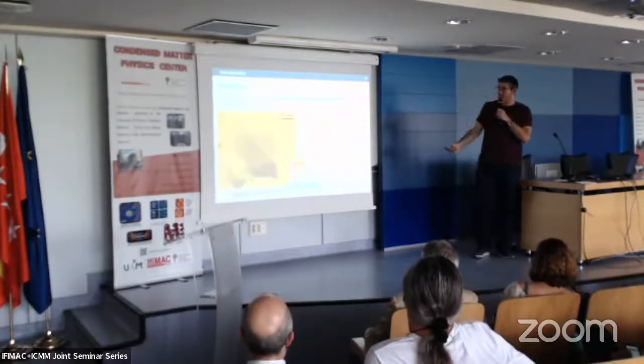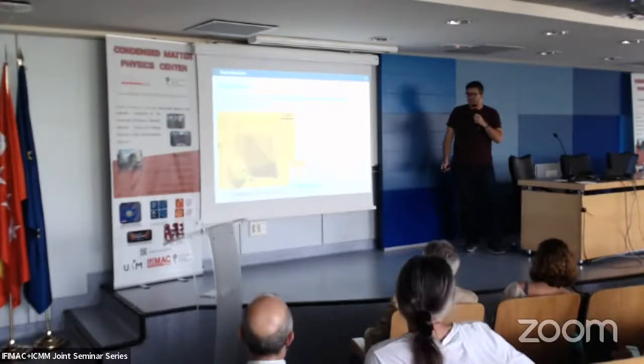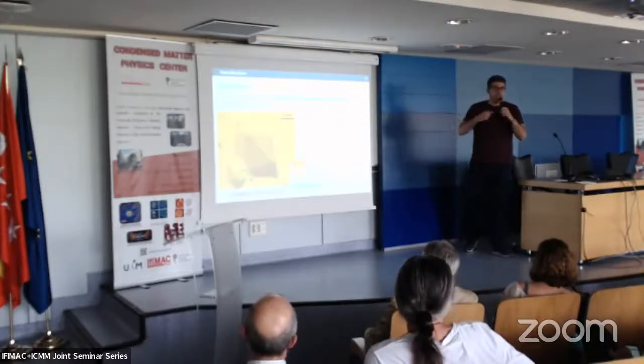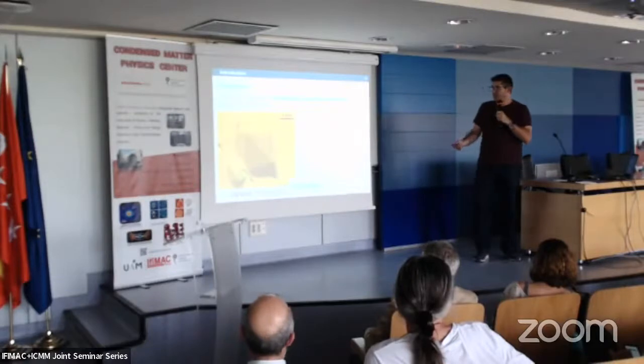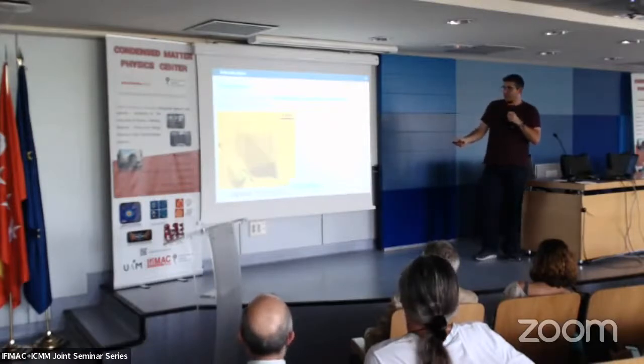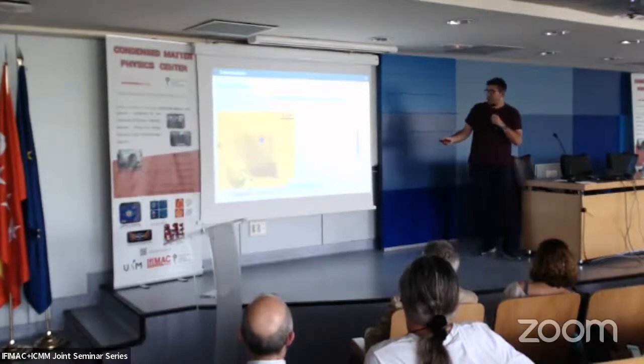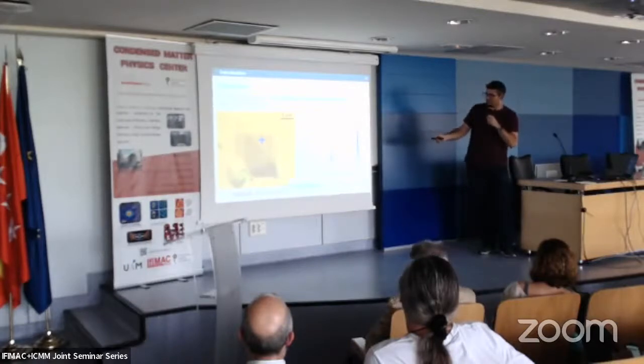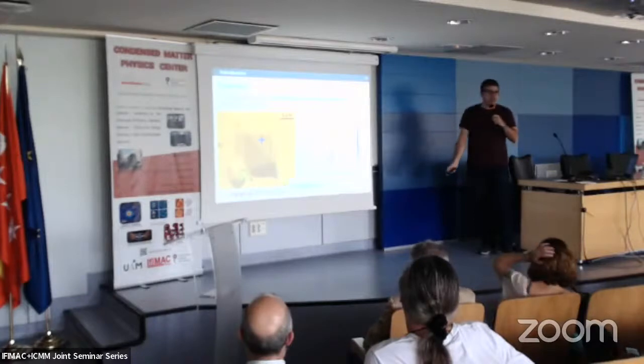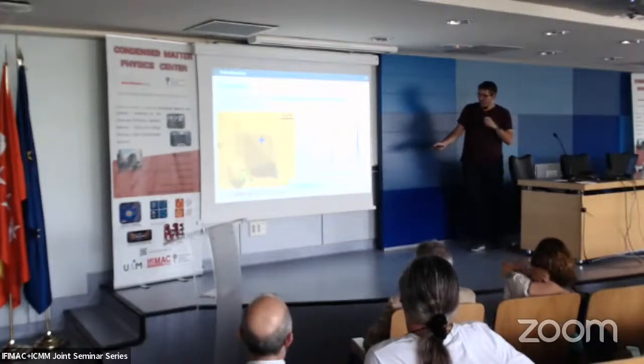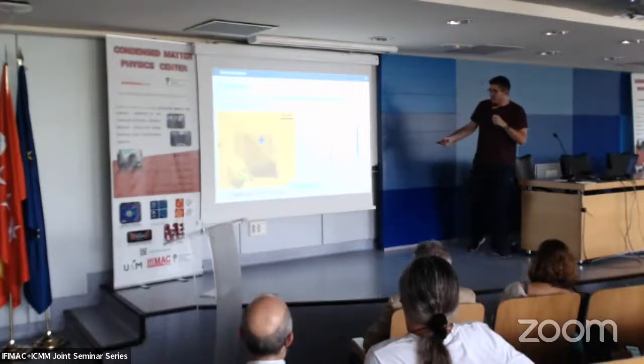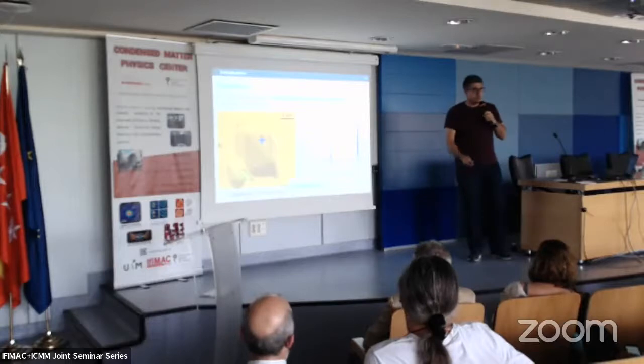So in our experiments, we use mechanically exfoliated graphene, which is the highest quality one, almost with no defects. We can see the flakes in an optical microscope. These areas with lower contrast are single layer graphene areas that we can check with Raman spectroscopy. You see these two characteristic peaks in the Raman spectrum of graphene, showing that this is single layer graphene. It is also high quality, because the D-peak, which accounts for defects, is not present here. So it's telling us that our graphene was very high quality.